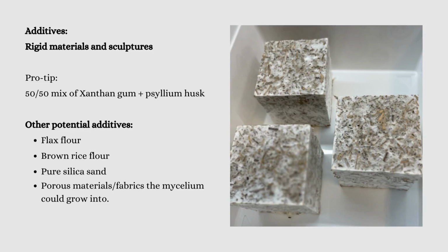Even in these cube shapes, it's important to use that, because the substrate, in this case, is these little tiny fibers, right? They're not granular. Doesn't mean that they're going to reach the corners of your mold, but because you're using this composite mix of flours, gelatin, mycelium, and your fibers, in this case probably hemp, you're going to be able to get into those corner spaces of your mold, so that it's fully myceliated and you don't have some empty gaps between your mold and your substrate.